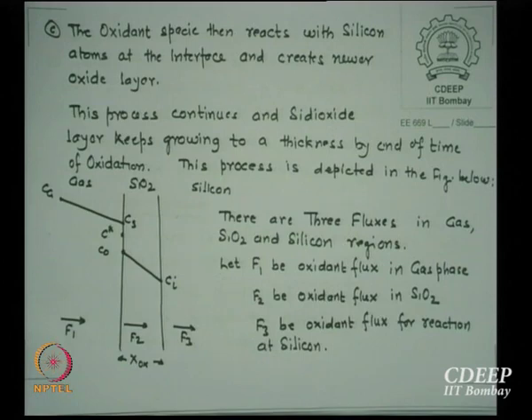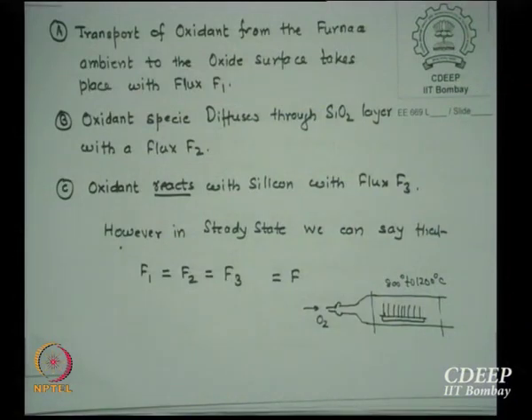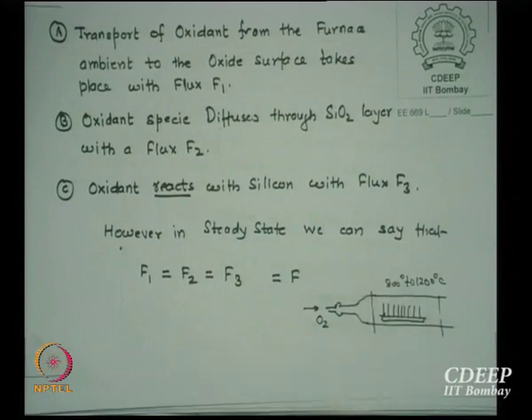We also discussed the other day that if the oxidant is coming, diffusing and reacting, the system has to be in steady state, and in steady state all fluxes must be equal. This we have done last time, I am just trying to push it again. We say F1 is equal to F2 equal to F3, and we call it F. This is just to show you how oxidation proceeds. Inside a furnace where the temperature is kept at 800 to 1200, wafers are vertically stacked on a quartz rack. Oxygen enters here and oxidizes the silicon.